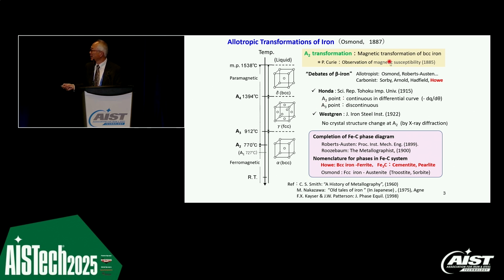So there was a long discussion between the allotropists and the carbonists, and Professor Howe belonged to the carbonists. And the first director of our institute, Professor Honda, contributed a little bit to settling this phase transformation question. He made thermal measurements and found a continuous change in the differential curve. That means it is not really first order, but a kind of second order phase transformation. Later, Westgren clearly showed by X-ray diffraction that there was no crystal structure change. After that, as I explained in the previous figure, came the phase diagram by Roberts-Austen and Roozeboom. Then Professor Howe's work on the nomenclature of the phase diagram was settled.